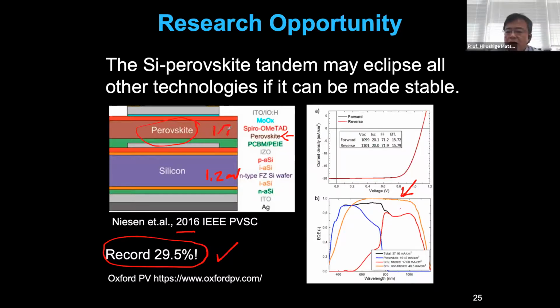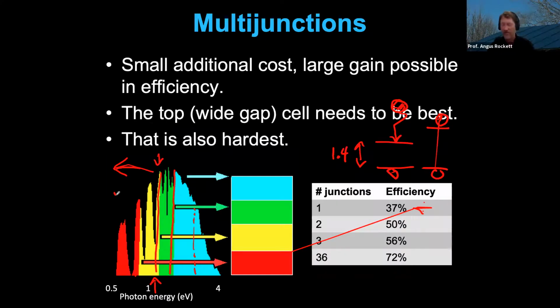So what about the higher band gap material on the top? For example, 2.5 eV, 3 eV. You don't gain very much. The problem is that you have to match the current. If you stack these devices up like this, you have to match the current. So it's the same amount of current that flows all the way through the stack from the top to the bottom. And so every solar cell has to make the same amount of current. And there just aren't very many photons in sunlight above about 500 nanometers. Sorry, below 500 nanometers. So the problem that you have is with this solar spectrum, that now you're out here in the upper range of this blue spectrum, and you won't have enough photons.